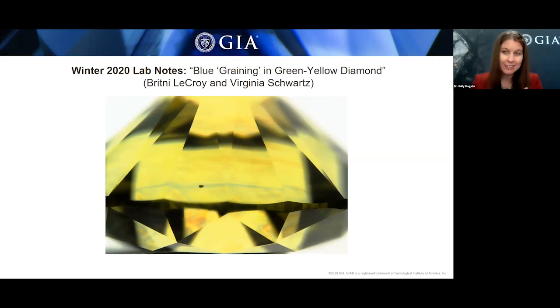Now, graining is related to distortion in the diamond's lattice structure, such as plastic deformation that occurred while the diamond was in the earth. Colored graining can be observed when this plastic deformation occurs along with nitrogen defects, typically. That's the typical case, but this diamond had the blue graining, which seems to tell a different story. The gemologists reasoned that the radiation damage was the most likely cause of this blue graining.